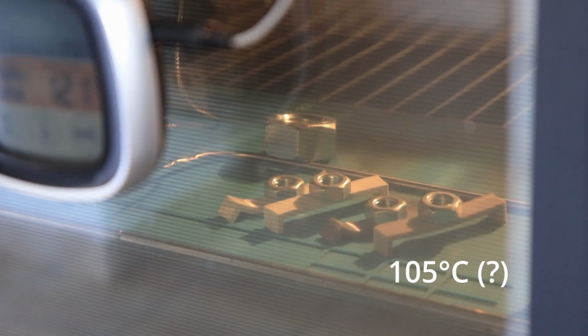This is a time-lapse video sped up 25 times, and this object is our resin from this experiment. I'm following this gap here because I want to record the temperature of the first deformation. Maybe it's happening now, approximately at 105 degrees Celsius, but it is not so obvious. And here actually it stopped with deformations.